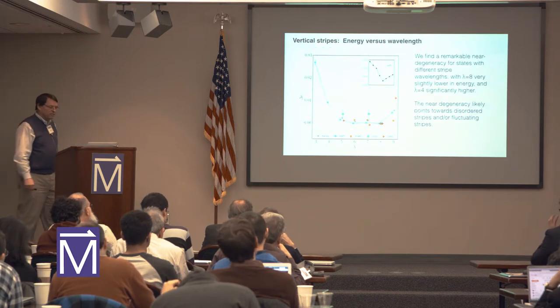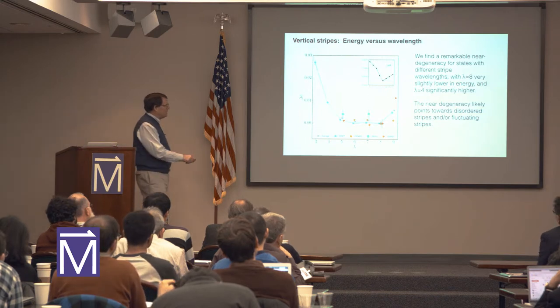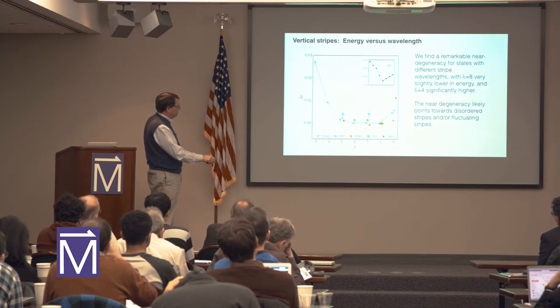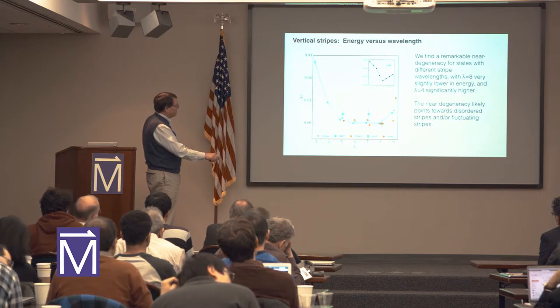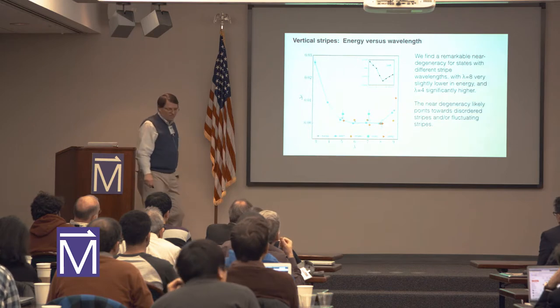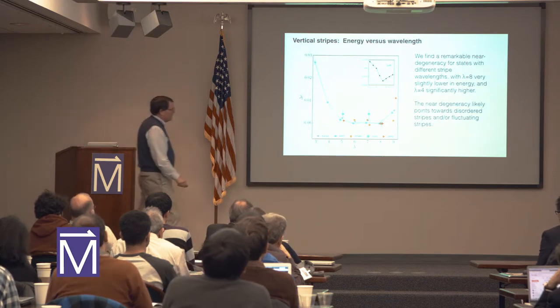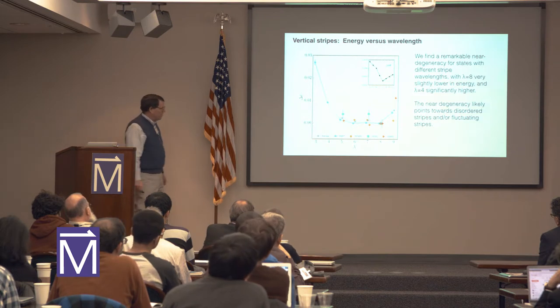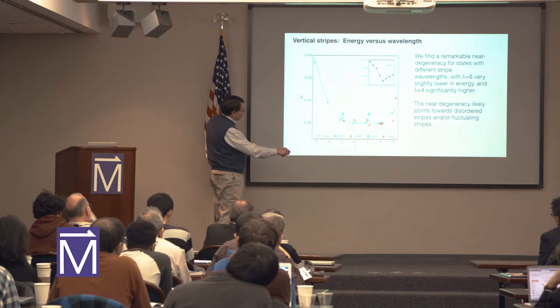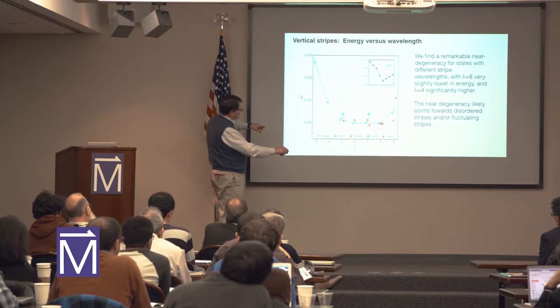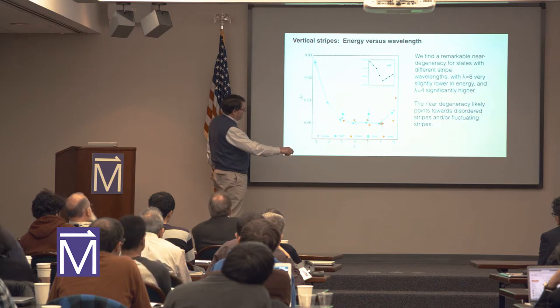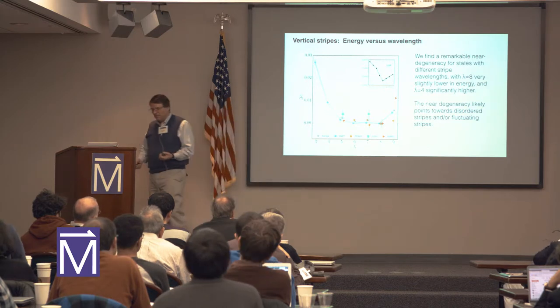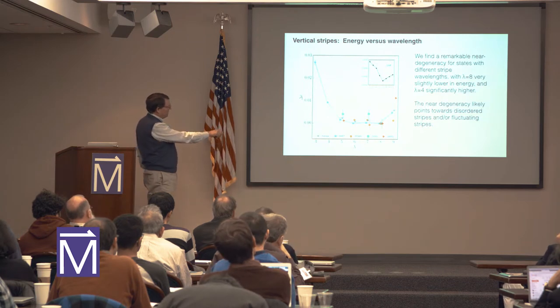Here are the results for the four different simulation techniques for the energy of the states versus the charge wavelength. At λ=8 are the filled stripes, and at λ=4, which is higher in energy, are the half-filled stripes. This is different from the t-J model, where we were saying that would have been the favored state. But what's more surprising is this very close near-degeneracy. Each of the four methods has been shifted so they all agree artificially at the filled stripe, and they're all very close to degenerate for a range down to about λ equals five, then they go up.